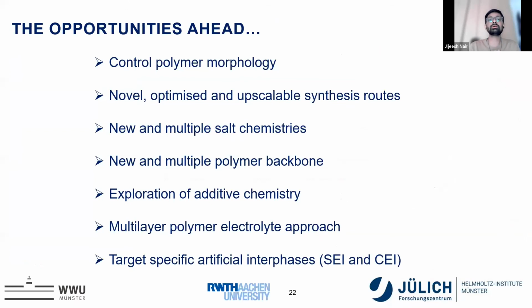So to conclude, I would say that in the case of polymer electrolytes, even though they have been around for the last 40 or 45 years, there are a lot of opportunities, especially with the introduction of lithium metal or other metal battery systems, metal-free battery systems, or anode-free battery systems. We can do a lot of things, especially by controlling the polymer morphology, by using new salt chemistries, multiple polymer backbone systems, or additive chemistry, which is very well established in liquid electrolyte systems but least explored in polymer electrolytes. This additive chemistry may do wonders even for optimizing the polymer electrolyte system. Then from the engineering side, you can have a multi-layer system, each layer tailored according to its requirements. You can make these kinds of artificial interfaces, which will give you much advancement compared to the previous generations of polymer electrolytes.